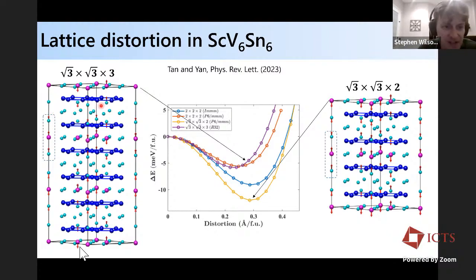Okay. So this is the structure that's realized below the charge order transition in the scandium 166 compound. But via DFT, the landscape has a lot of different competing distortions which can potentially occur. And the energetically favored one from a simple DFT approach is this √3 by 2. So the same in-plane reconstruction, but a shorter superlattice along the c-axis.